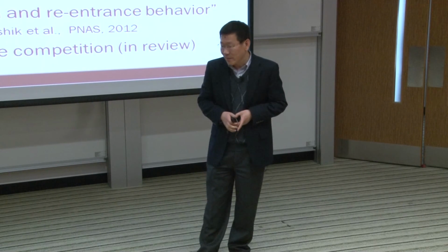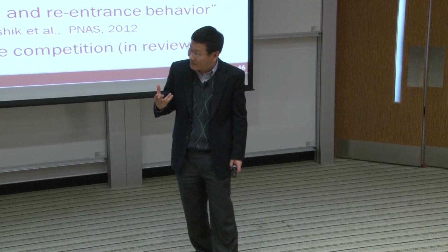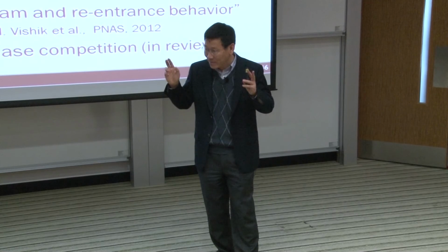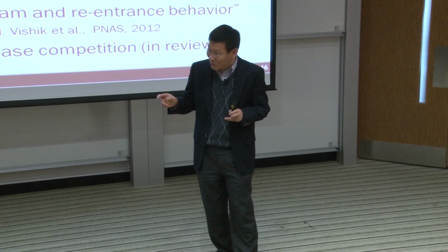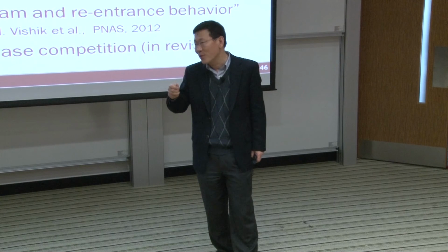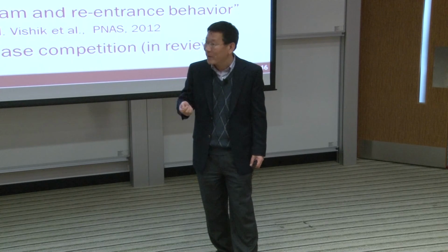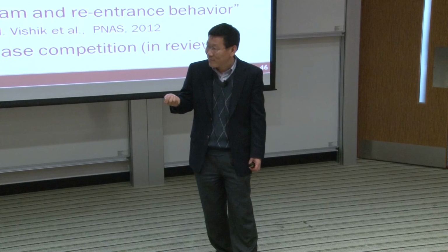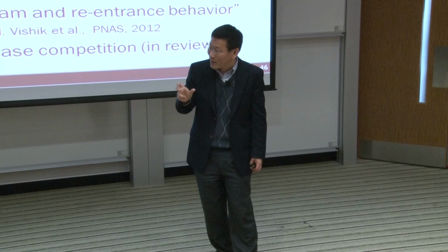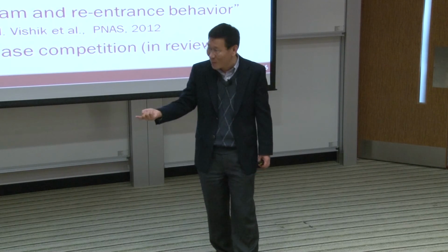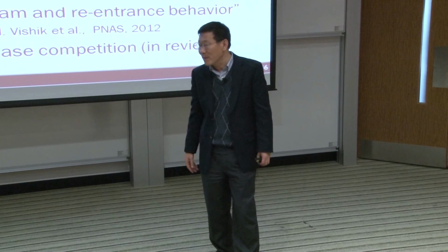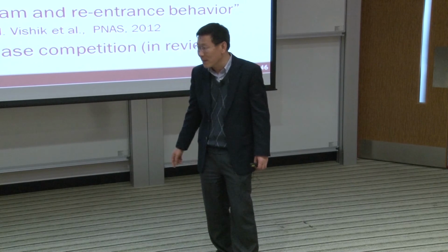Okay. Of course, superconductivity is a pairing, okay? But the pseudo gap, as I said, is still a subject of investigation. Take the simplest, the most naive form of the charge density wave, and it will also have an energy gap. Okay, so if there's a superconductivity and charge density wave, they compete for the same states to form their own advantage. So it could be a charge density wave, but that's the most naive and simplistic interpretation.